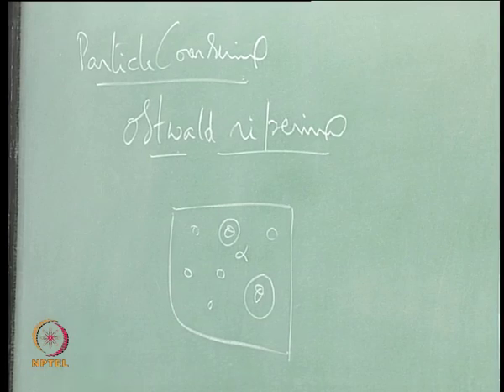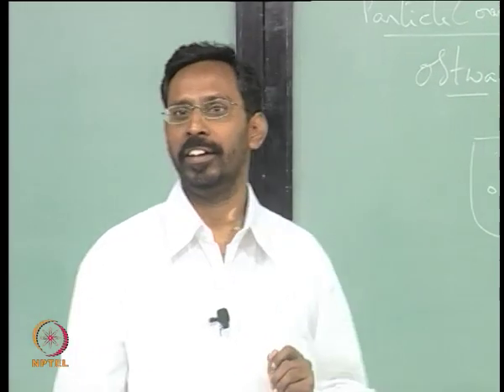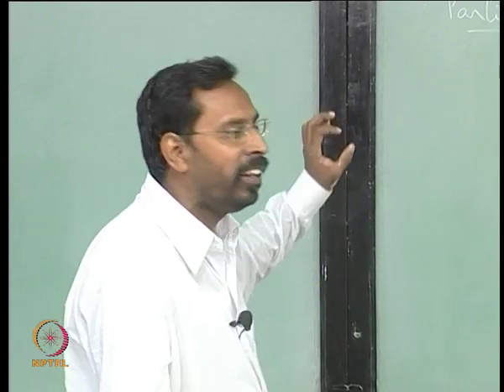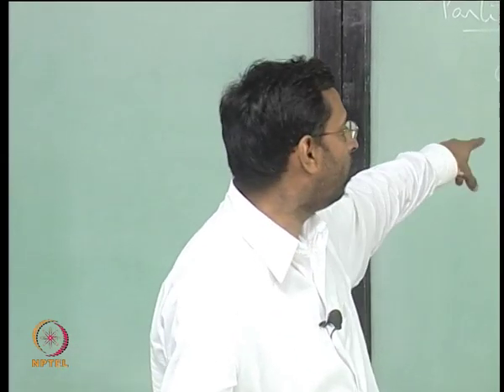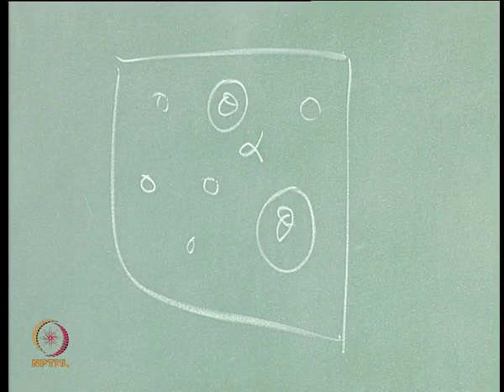The composition around that theta, copper will be less. Why? Because the diffusion has occurred for a longer time. It has nothing to do with diffusion. It is the curvature effect. Because of the curvature effect, you would see actually the free energy of that two particles is different.